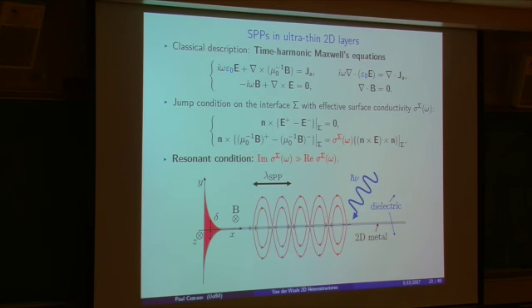And this is described, sorry for a few equations here. So we have very simply here Maxwell's equation in the free space. And we can describe what happens here by having an effective surface conductivity. So that will allow charges and currents to be created on the surface. And so the physics tells us that the tangential component of electric field should be continuous, going through the layer, whereas because of the induced currents, due to this oscillation of charges, the tangential component of magnetic field will see a jump, which is linked precisely by this effective surface conductivity.